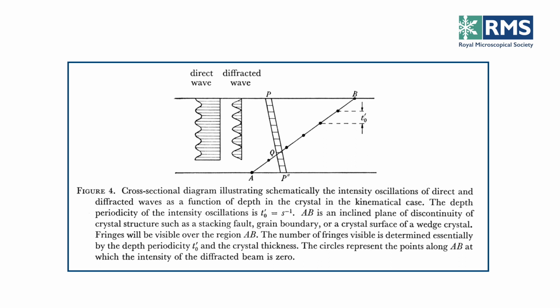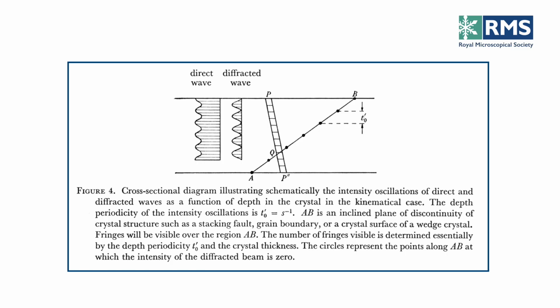Well, while I've got this slide on, I should also say that suppose instead of having a dislocation, you have a stacking fault running across it. When the electron beam actually traverses the stacking fault, there's a phase change because the atoms on the two sides of the stacking fault are in the wrong order, and that leads to a change of phase in the diffracted beam. And that gives you contrast. And that will also be an oscillating contrast depending on the oscillations of the diffracted beam. I'll show you an example of that in stainless steel in a few minutes.